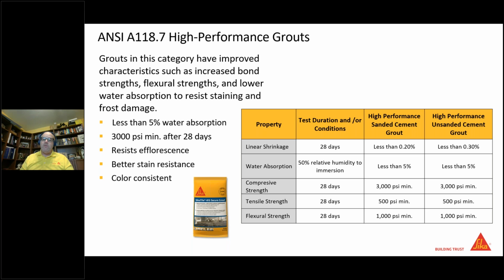Compressive strength. This is a really impressive number. Compressive strength after 28 days, it needs to meet 3,000 PSI minimum. That's a pretty darn durable grout right there. And that's how we help resist staining or keep that color consistency and resist efflorescence. Tensile strength, 500 PSI minimum. Flexural strength, 1,000 PSI minimum. So as you can see here, this testing for this product is, let's just say it's a hard test to pass to be able to meet this high performance grout. And when you can meet that and you know that you've got this information behind it, or this quantification of this product behind it, to get to that 118.7 high performance, you're getting a good grout from these manufacturers.